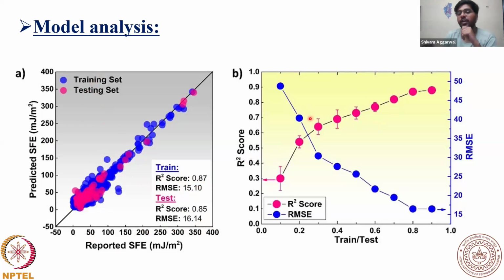And here is the R2 score and the RMSE, how it decreases and increases as we increase and decrease the train test split. Just suppose we take 0.2; if I take 0.3, it means 30% is the test set and 70% is the training set. If I choose 0.4, then 40% is the test set and the train will be 60%. So here you can see how the RMSE or R2 score increases and decreases. So the R2 score has to increase as the test set is decreasing.